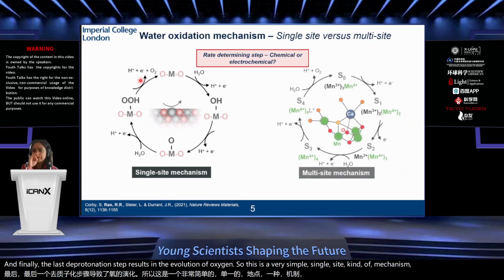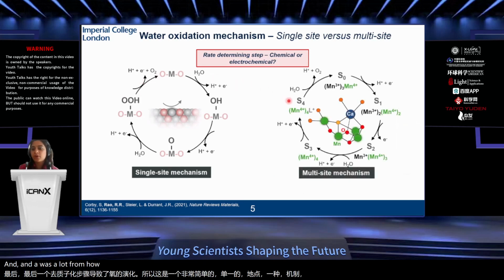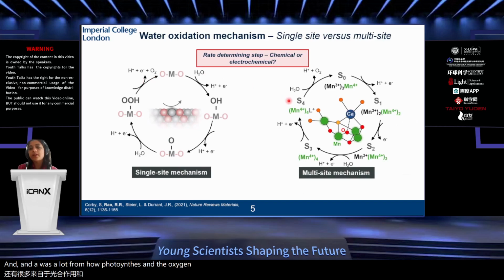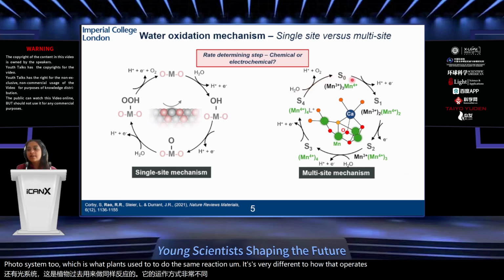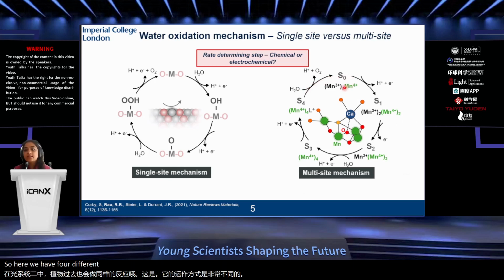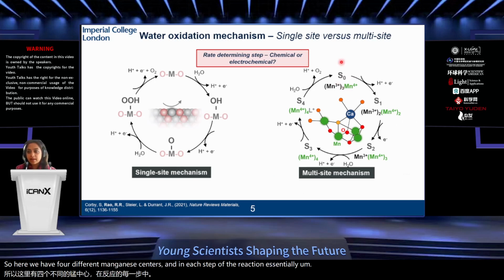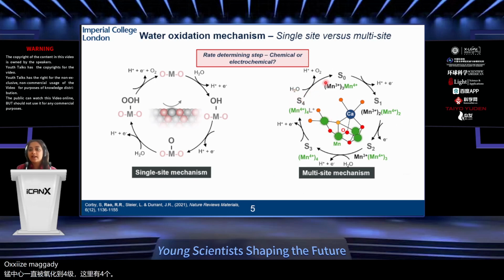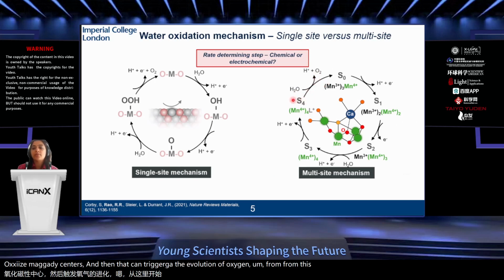And it differs a lot from how photosynthesis and the oxygen evolving complex, for example, in photosystem 2, which is what plants use to do the same reaction. It's very different to how that operates, right? So here we have 4 different manganese centers, and in each step of the reaction, essentially a manganese center is oxidized all the way going to this S4 state where you have 4 oxidized manganese centers, and then that can trigger the evolution of oxygen from this very oxidized complex.